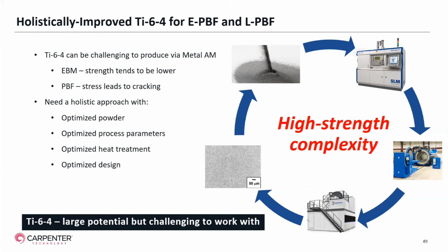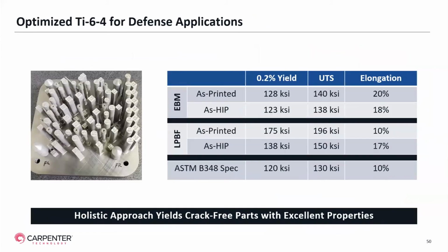And so when we looked at this problem a couple of years ago, we realized that there was no one answer to solving this problem. It really needed a holistic approach with the powder, process parameters, heat treatment, and design to be able to make Ti-64 components on either a laser powder bed fusion machine or an electron beam machine, which don't crack and which have sufficient properties to meet whichever ASTM or other standard needs to be met. And Joe, if you want to go to the next slide.